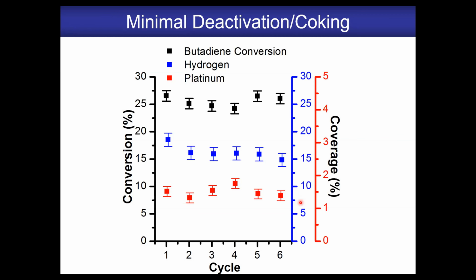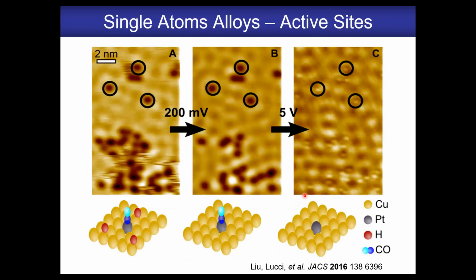And now, because we have the scanning tunneling microscope, we can ask the question, where does each reaction step occur? So this is STM on the left here, which is basically shown in this cartoon here. This is an experiment in which we have platinum atoms on a copper surface. We've exposed it to hydrogen. The hydrogen is dissociated, spilled over. Hydrogen's the red dots here. And then we've adsorbed a little bit of CO, 1 or 2%, to just selectively bind to the platinum sites, because it binds to copper so weakly. So what you see here is the black circles are the CO molecules adsorbed on the platinum atom sites. And then all the streakiness around them is that fast diffusion of the hydrogen through quantum tunneling.